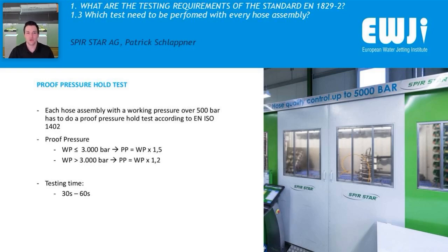Additionally, every hose assembly over 500 bar has to undergo a proof pressure test. So in the end, each hose assembly which leaves our facility is pressure tested according to the proof pressure test. The proof pressure on assemblies with a maximum working pressure smaller or equal to 3000 bar is the working pressure multiplied by the factor 1.5. The proof pressure on assemblies with a maximum working pressure over 3000 bar is the working pressure multiplied by the factor 1.2. The testing time is between 30 seconds and 60 seconds.